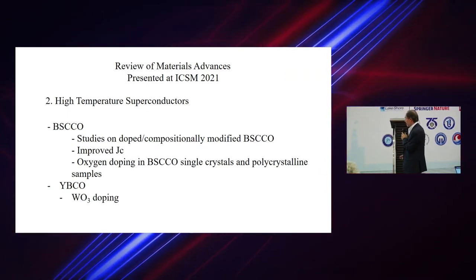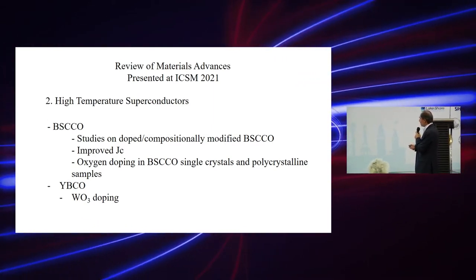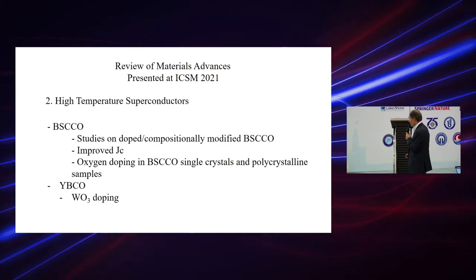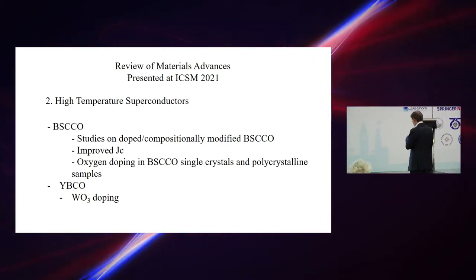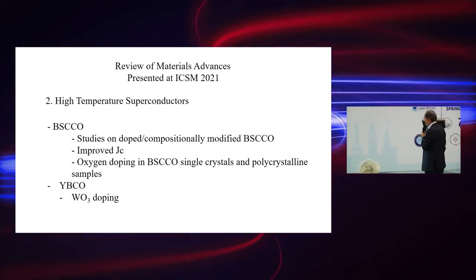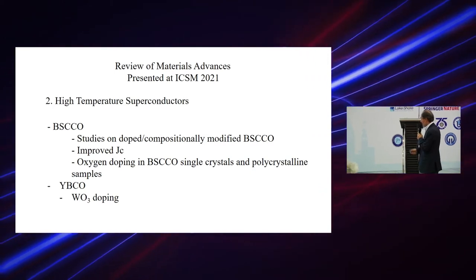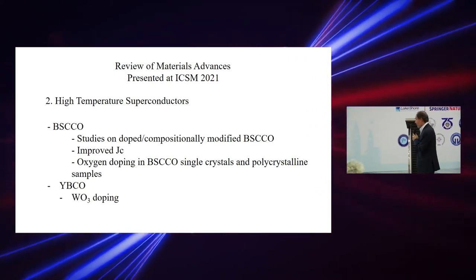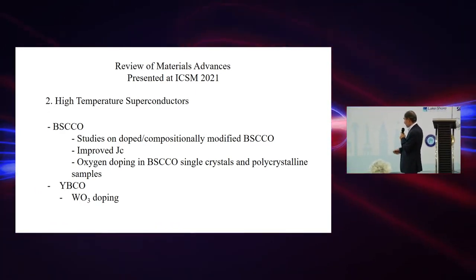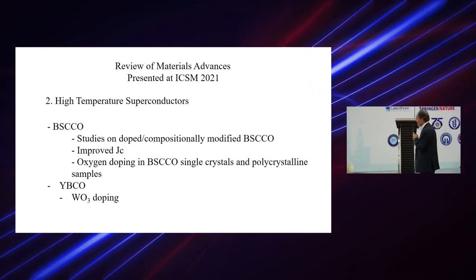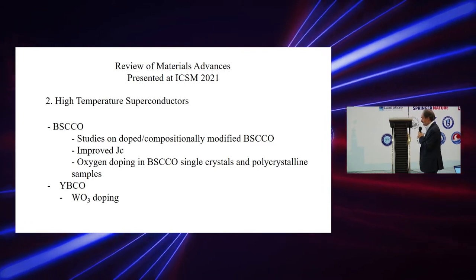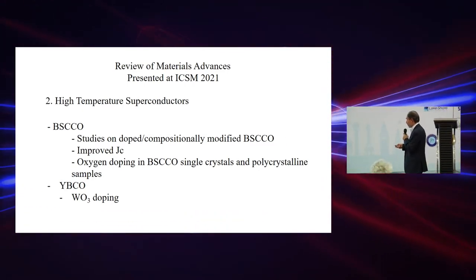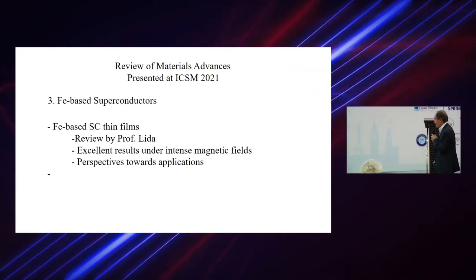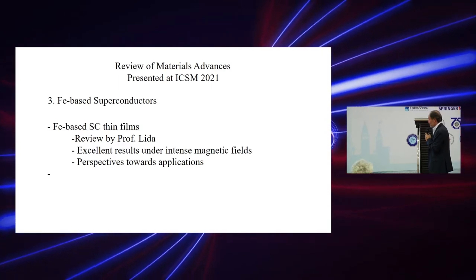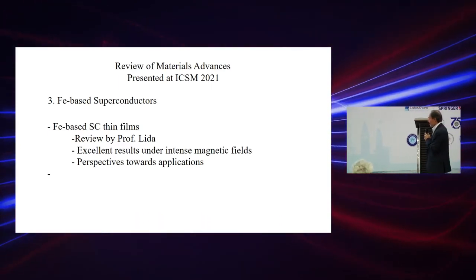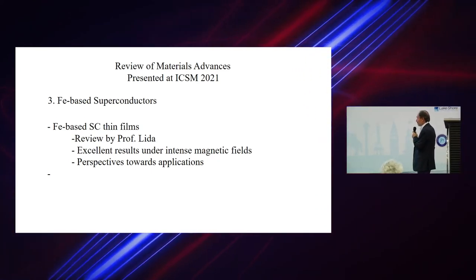And concerning high temperature superconductors, I give two examples. In BSCCO superconductors, studies concerning doped or compositionally modified BSCCO have been shown to improve the JC values, and oxygen doping studies in BSCCO single crystals versus polycrystalline samples were also shown to be very beneficial. In this case, single crystals exhibited much better results than the polycrystalline samples. And concerning YBCO, I remember a study of the effect of tungsten oxide doping. Concerning iron-based superconductors, there was a very nice review by Professor Lida, where he showed excellent results under very intense magnetic fields and the perspectives for their applications.